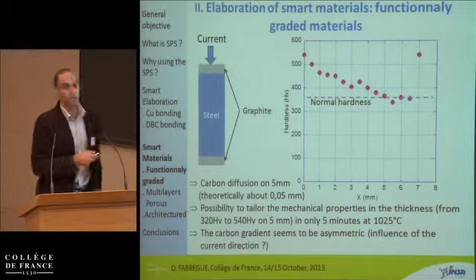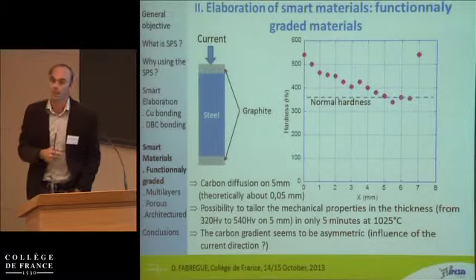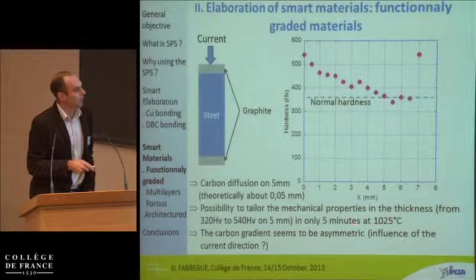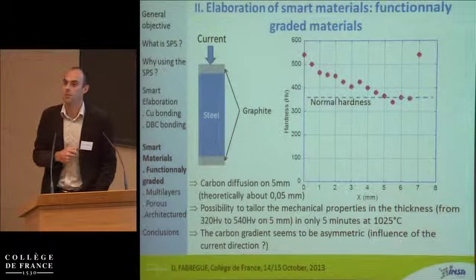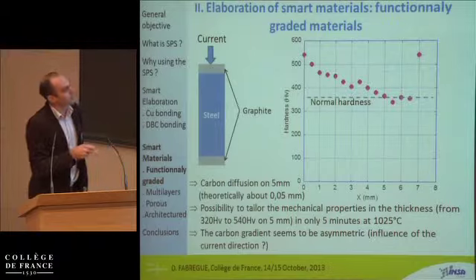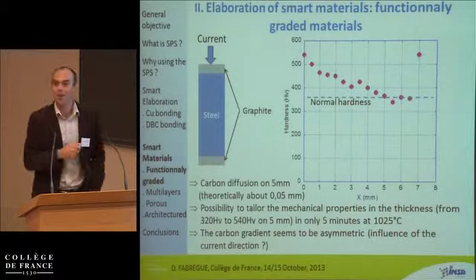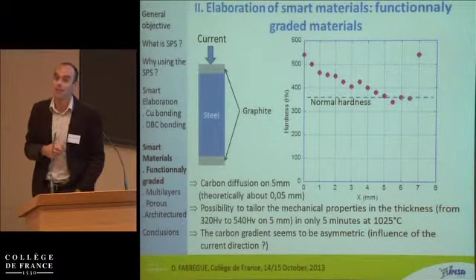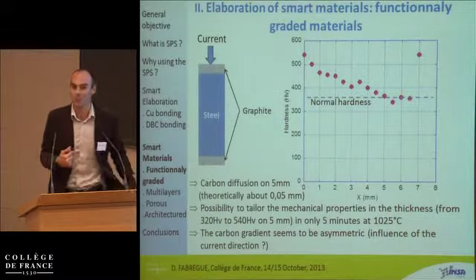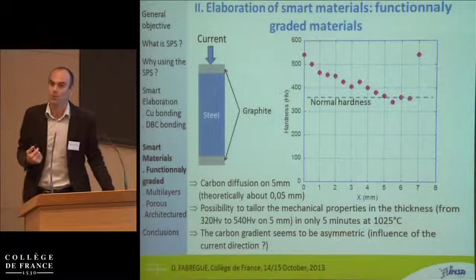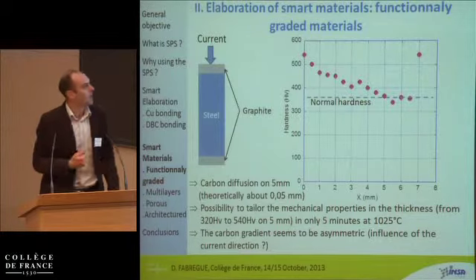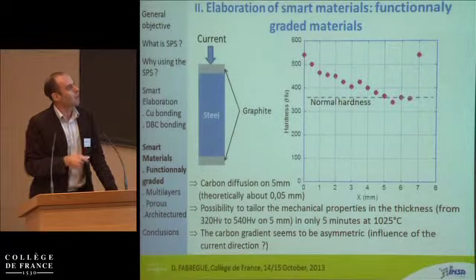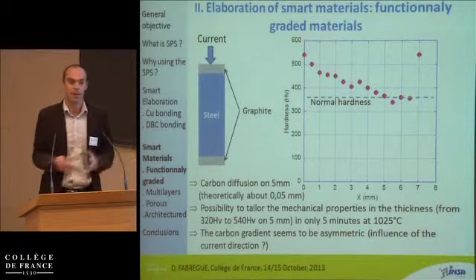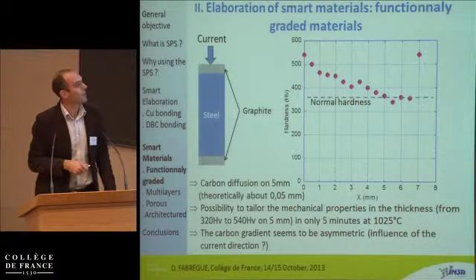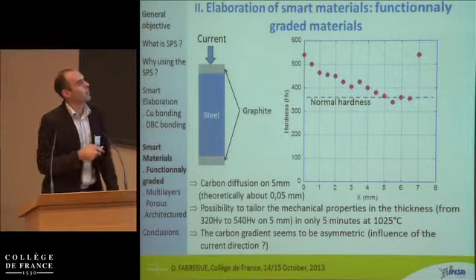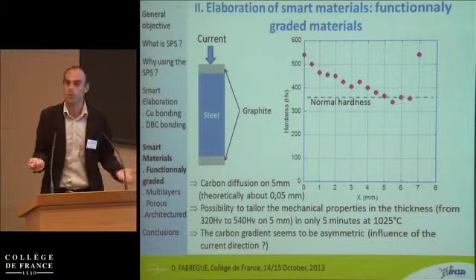This is the normal hardness for 100% martensite in that steel. This has been done for 5 minutes at 1025 degrees C. As you can see, you have a gradient of carbon which is about 5 millimeters in that case, which is far larger than you should have if you look at the diffusion coefficient of carbon in iron. So that means that we can have this kind of really large gradient in one material, and you can then tailor the mechanical properties according to the process parameters.